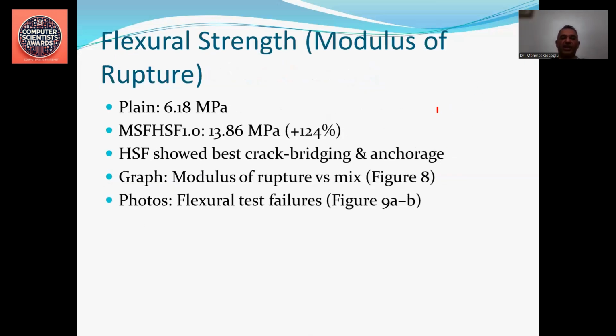The flexural strength, in other words, modulus of rupture, was also tested. The plain concrete reached a value of almost 6 megapascal. By using hybrid fiber, this almost doubled to 13 megapascal. It indicates almost 100%, 125% increment in the flexural strength. Hook steel fibers showed the best crack bridging and anchorage, so they increased the flexural strength more than the micro steel fibers.